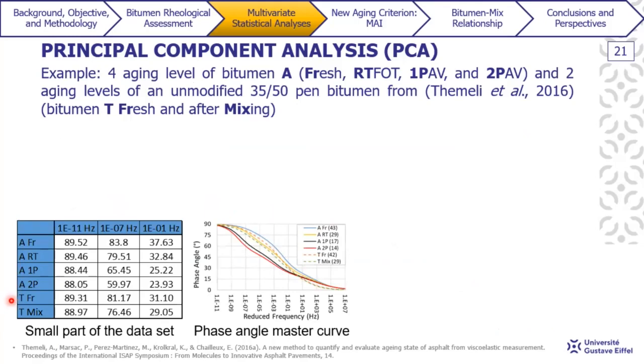And here I just put 2 more bitumens that I took from the literature, which is an unmodified 35 pen grade bitumen from Themeli and coworkers, which is TFR, it's T fresh, and T mixing is right after mixing. So here each line represents each bitumen used in this example, in this small part of my data set. And here the columns represent the phase angle corresponding to each of these reduced frequency values, which are represented by the markers here on the curves.